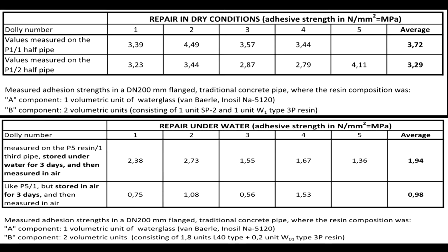Comparing the numbers in Table 2, we can see that the specimens made underwater but stored in dry and warm conditions between 25 and 30 degrees centigrade show substantially lower adhesion than the ones stored underwater. The loss of water means a partial drying out of the lining composite, which leads to lower adhesion.